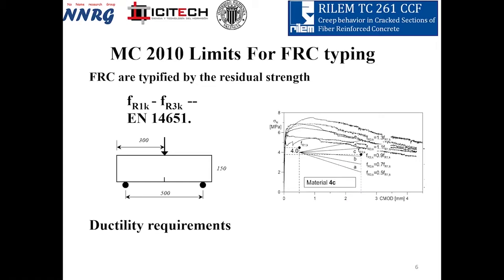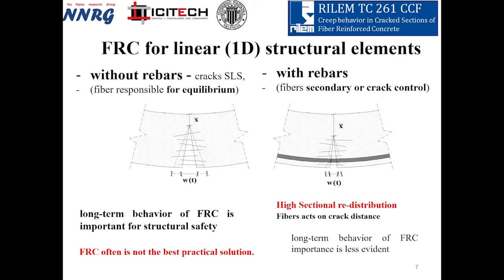With this concept, we develop lots of structural behavior aspects with fiber reinforced concrete. It's clear if we try to analyze a one direction structural element, if you use only fibers, you will have a crack, and the fibers are responsible for the equilibrium. And in this case it is clear that you have problems, or you must consider the effect of long-term behavior of the fiber in this crack. Because if the fiber reduces its contribution, deflection will increase. Even in this case, either you work at a very high level of fiber content or residual capacity of the fiber reinforced concrete, or you work with enough safety coefficient, and then you work in not cracked specimens.